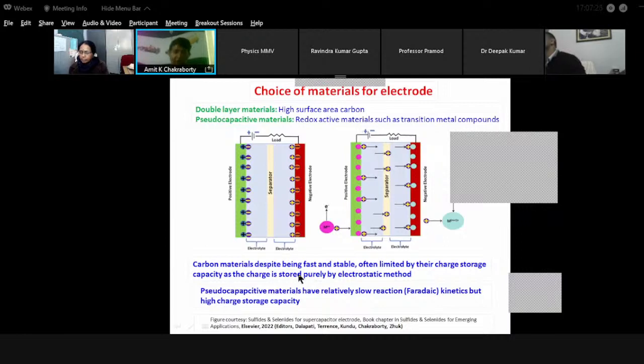And the typical choice for double layer materials is carbon nanostructures, which have large surface area essentially. Even then, they have some good properties, but also some limitations. For example, carbon materials, despite being very fast and stable, are often limited by their charge storage capacity, as the charge stored is purely by the electrostatic method. There is no redox mechanism taking place with carbon materials.